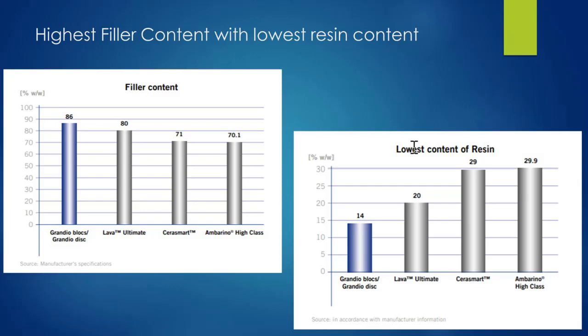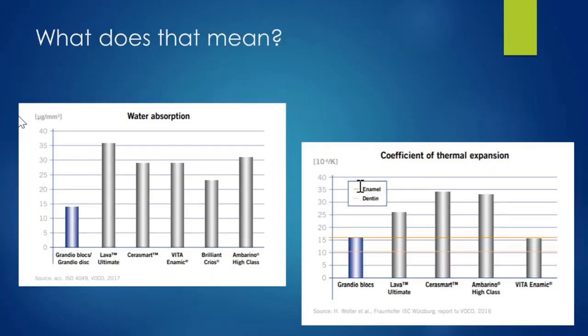So when we look at the amount of filler, Grandio block again is leading the rest of the pack. Again, when we make a decision in our office about which material we're going to use, I'm always going to base that decision on the science. It's got to be based on the best decision I can make, given the best information that's available to me. So when I look at the amount of filler and I see that it also contains the lowest amount of resin of any of the other resin ceramic hybrids, I say, well, what does that really do for me? What that does for me is it decreases the amount of water absorption that we see with these restorations, but more importantly, it gives us a coefficient of thermal expansion that most likely resembles enamel and dentin.